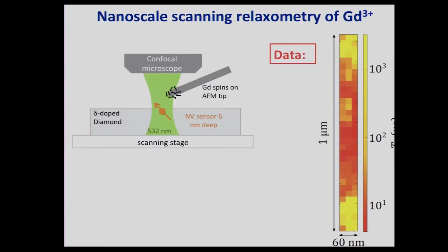So then to show this a little bit more clearly, we took an image. This is an image where we're scanning 60 nanometers in one direction and 1 micron this way. And in the color scale we plotted the T1 of the NV center as this gadolinium tip is scanned over the NV. And one sees that the T1, where it's red, is again almost 3 orders of magnitude smaller than when the tip is far away. So we can really start imaging the gadolinium.